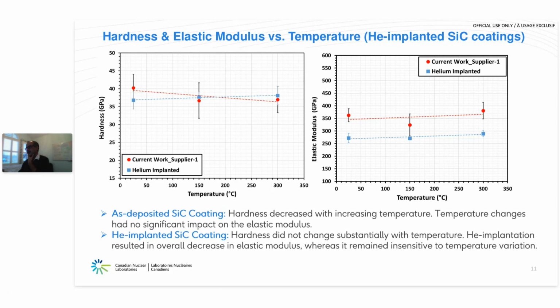increase in temperature. And this may possibly be coming from the fact that there might be a nanoporosity forming within the localized region, as I was showing in my previous slide, which is causing the elastic modulus to drop. But to know the exact reasons, we have been pursuing the TEM analysis of the specimens taken from the indented sites and also away from the indented sites for these samples from both helium implanted as well as the as deposited silicon carbide coatings.